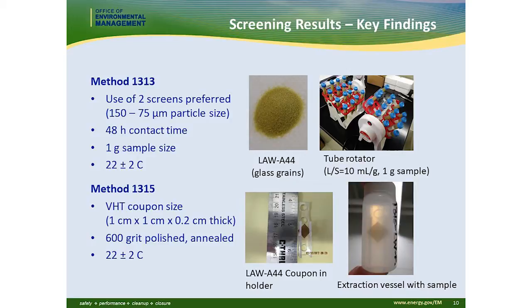For method 1315, we used the same coupon size as the VHT coupon, 1 by 1 centimeter by 0.2 centimeters thick. It was polished to 600 grit and then annealed, same temperature. And what you can see here is a holder that was developed for it, very simple fabrication, a piece of plastic that holds the test coupon with minimum contact. And then we have a very fancy test vessel that we put it in, a Nalgene wide mouth container. You can see the image of the coupon and the holder within there, which allows us to exchange it very readily.